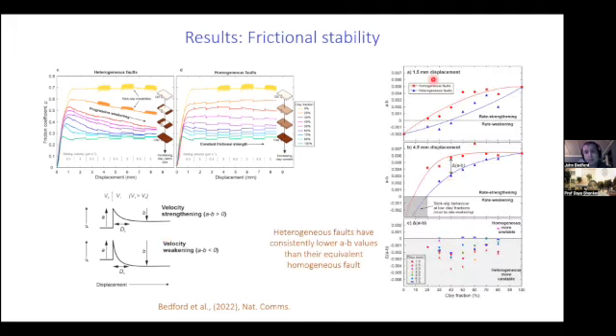So on the right here, in panels A and B, I've shown you the A minus B data for the homogeneous faults in red and the heterogeneous faults in blue as a function of clay fraction. And the two panels A and B are just different displacements from the experiment. And you can see that the homogeneous faults have consistently higher A minus B values, so they are more stable than their heterogeneous counterparts. And what we also did is we analyzed, for a given clay fraction, the difference between the heterogeneous A minus B values and the homogeneous A minus B values, this delta A minus B term, for every displacement throughout these tests. And we find that almost all the values fall within this lower part of panel C, showing that the heterogeneous faults always have lower values and are therefore more unstable than their homogeneous equivalents.